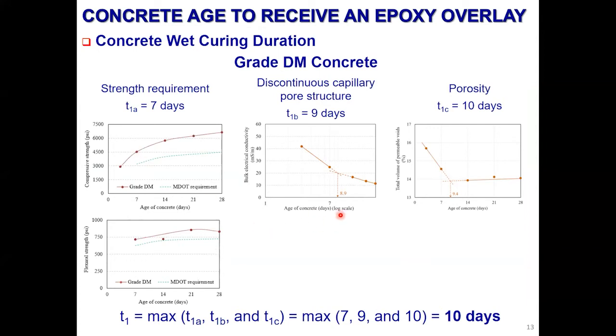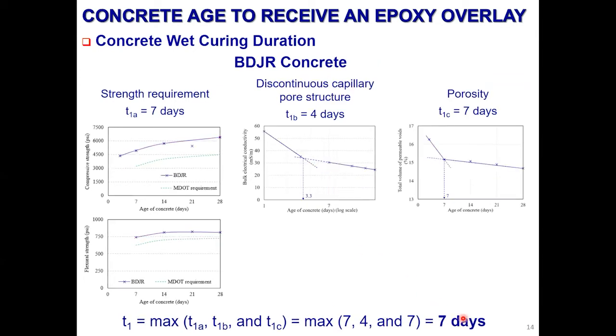But in order to have a durable concrete, we need to have the minimum permeable voids and the discontinuous capillary pore structure. We can evaluate that using bulk electrical conductivity and porosity testing. With that, we can determine the minimum curing duration. In this particular case, with the mix with slag, we need to wait at least 10 days. This is the wet curing duration.